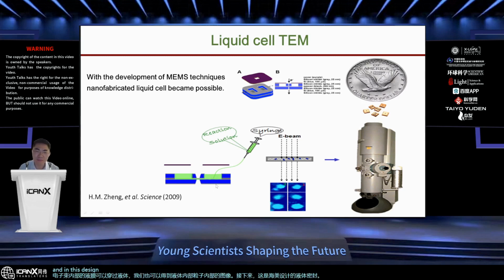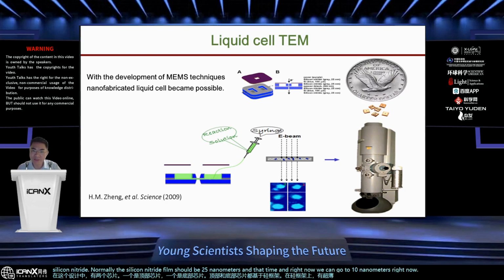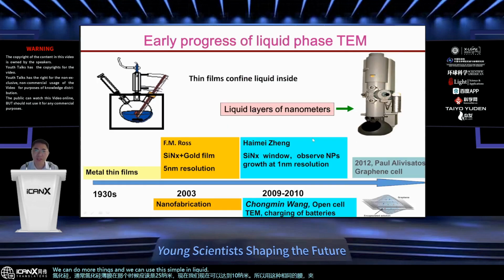Next, this is a liquid cell designed by Jaime, my previous advisor at Berkeley. In this design, two chips sandwich the liquid, as I mentioned, one top chip and one bottom chip. Both chips are based on a silicon frame, and on the frame is an ultra thin silicon nitride film. Normally the film was 25 nanometers at that time, and now we can go to 10 nanometers. With such a thin membrane sandwiching the liquid, we can image samples in liquid.